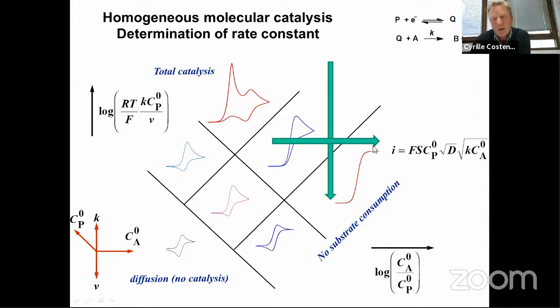And of course, experimentally, you're not always in that situation, but as you can see, you can play around with the scan rate or the concentration of the substrate. If you increase the scan rate, for example, you will move the system down and you may get a chance to reach the zone where you observe the plateau. Or if you're in this situation, you can increase the concentration of the substrate to move the system toward this interesting zone where it's easy to get the rate constant.